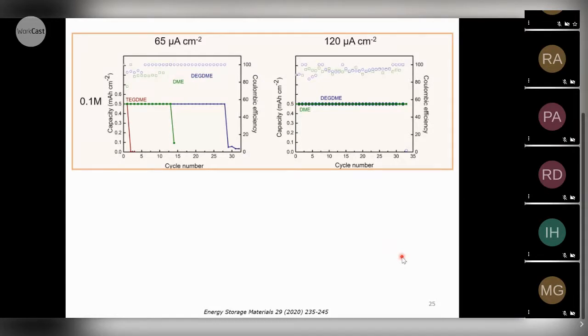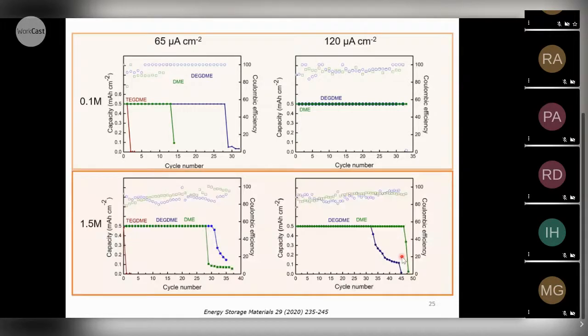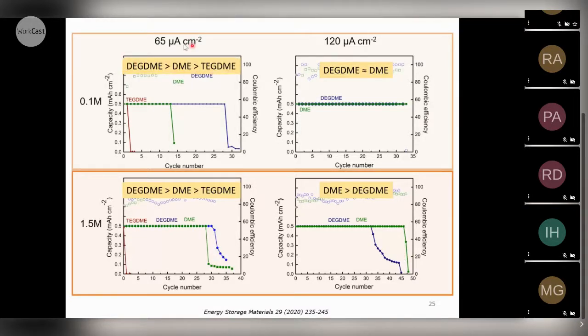So then what we did, just simple experiments using commercial carbon papers, looking at low concentration and two rates, and looking at a higher concentration and two rates. And then we came up with this trend. We can see that here it follows the same trend, and here it differs. So we wanted to know which solvent is good depending on the characteristics of the batteries, or the energy density, current density.